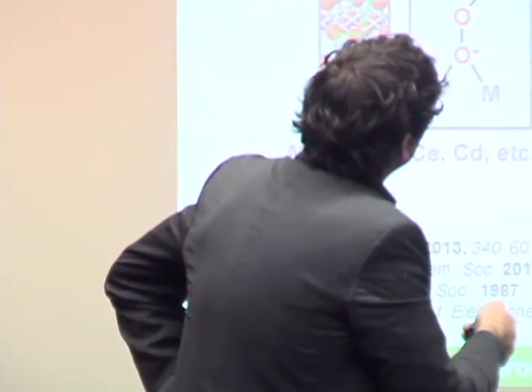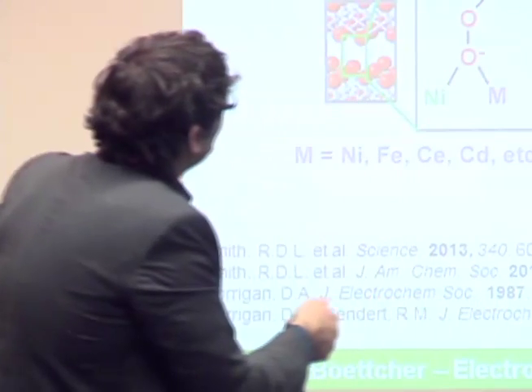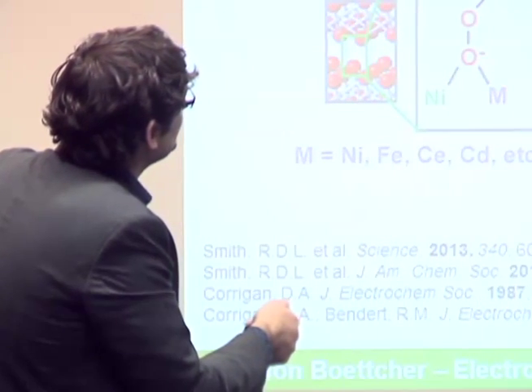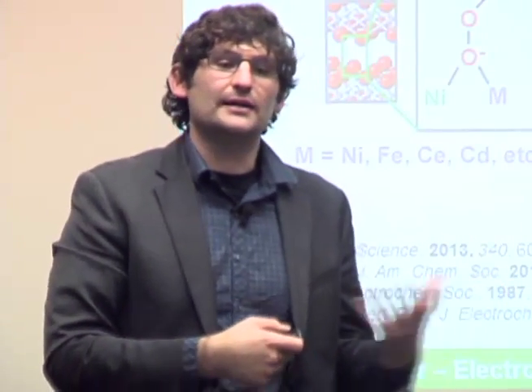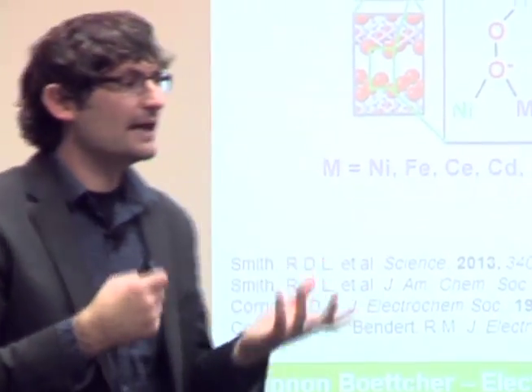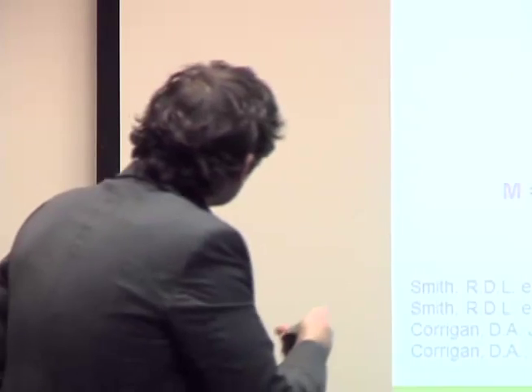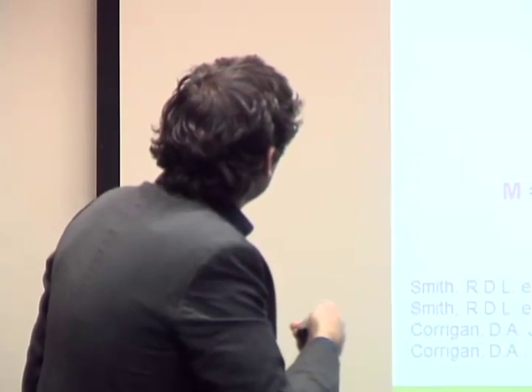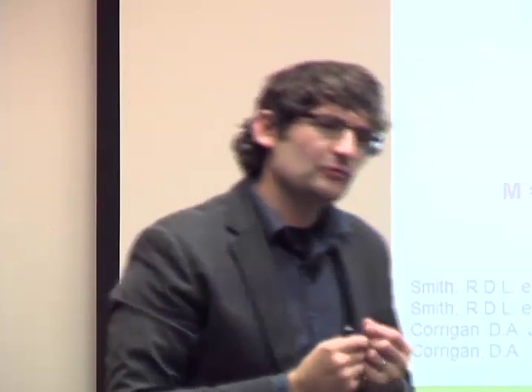And what's interesting is this wave, this nickel 2,3 oxidation wave, its position on the potential axis depends on the amount of iron you alloy in the nickel iron oxyhydroxide. So what that's telling you is you're changing the electronic structure. You're changing the energy at which you can pull electrons out. So you're moving the density of states, the D band or something of the oxyhydroxide. We also wanted to look at the thin film, the actual electronic conductivity, because as I mentioned before, you really do need to be able to move electrons through these films to get them to the active sites. And if this electrical conductivity was sufficiently high, even in thin films, it could make a difference.